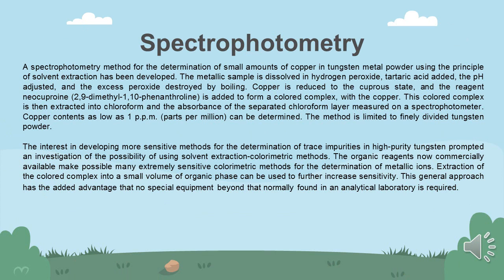Spectrophotometry. A spectrophotometric method of determination of a small amount of copper in tungsten metal powder, using the principle of solvent extraction, has been developed. The metallic sample is dissolved in hydrogen peroxide, tartaric acid added, the pH adjusted, and the excess peroxide destroyed by boiling.